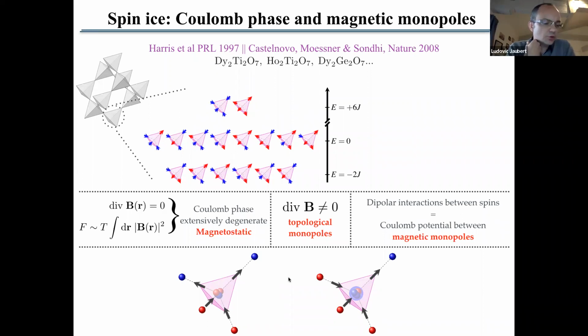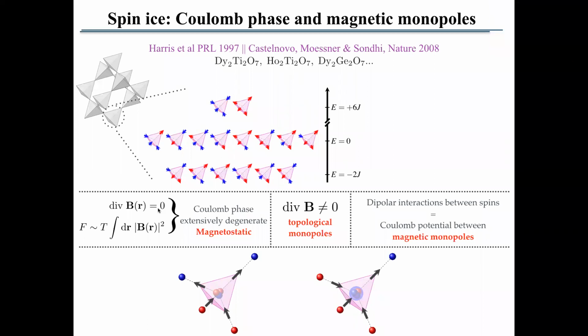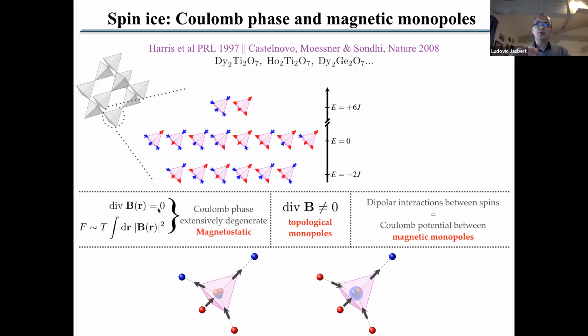So in 2D materials, for example, if you take the pyrochlore lattice and you put a strong magnetic field in the 1-1-1 direction, you get a magnetization plateau. The magnetization plateau consists of 1/4 of the spins which are aligned along the magnetic field, and so they are frozen into the state. And the other 3/4 of spins form a decoupled Kagome lattice. And this decoupled Kagome lattice has exactly the same divergence-free, zero divergence condition that you have here, which means that excitations out of this would create magnetic monopoles. And actually, by further enhancing the magnetic field, you get a condensation of these magnetic charges.